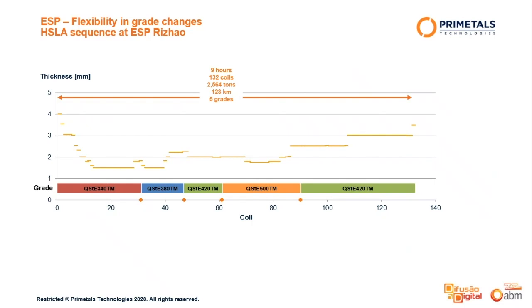During operation, widths, thickness and grades can be flexibly adjusted. Flying gauge changes are a standard procedure at ESP lines. Grade changes are calculated in the caster with the mixer expert, and with the digital twin function of this tool, such changes can be even tested in advance in the office before execution. We see here a sequence which produced 132 coils in 9 hours, more than 2,500 tons. And in total, we had 5 grades produced in this sequence.